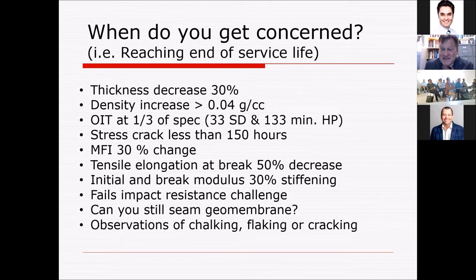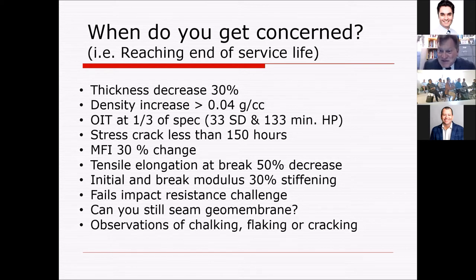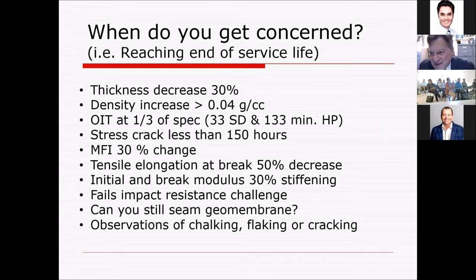One of my favorites is fails in impact resistance test — championed by a dear friend André Roland and Ian. I think it's very good particularly for cold region climates. The best practical tell that I know is: can you still seam the material? If you can't seam it, it's certainly aged enough that you're well beyond its service life. Observation of chalking, flaking, and cracking — yes, I've written about this quite handily and published it. It's a nice checklist and if you have additions to it, I'd like to hear from you.